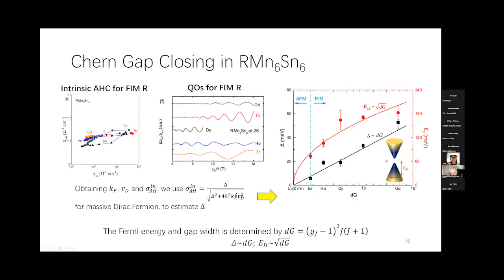So we compare all the intrinsic anomalous Hall conductivity for these rare earth 166 compounds, and we also detect a quantum oscillation for the samples. Using these parameters, we're using a massive Dirac fermion model. We can estimate the Chern gap and estimate the Fermi energy for the massive Dirac fermion. We found an interesting scaling law.